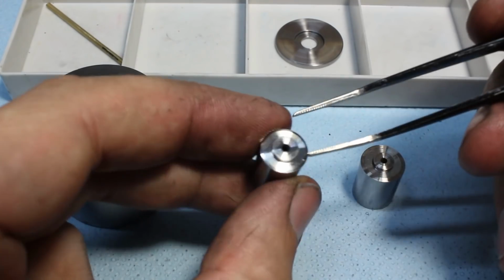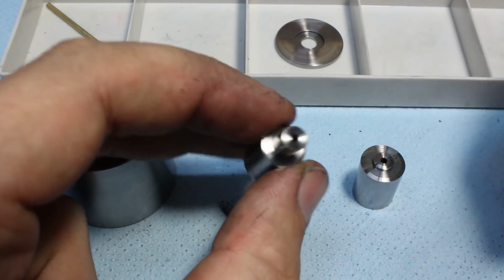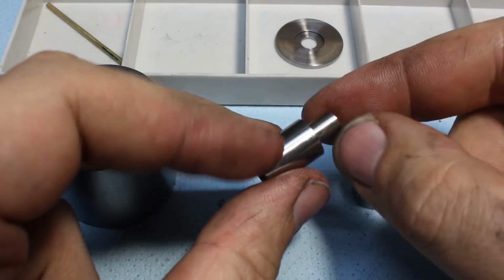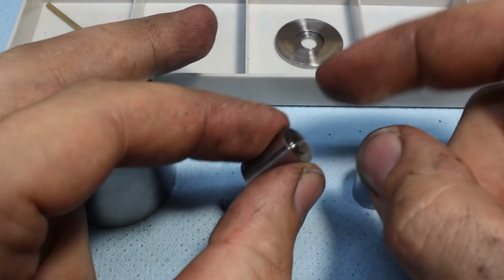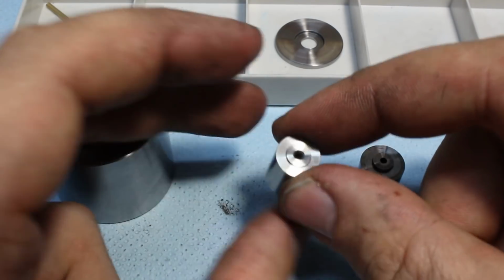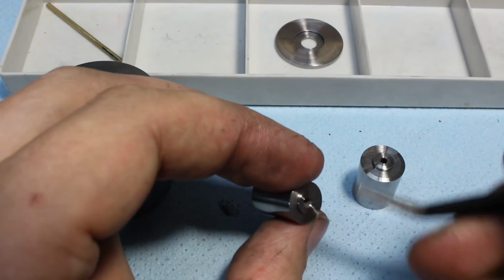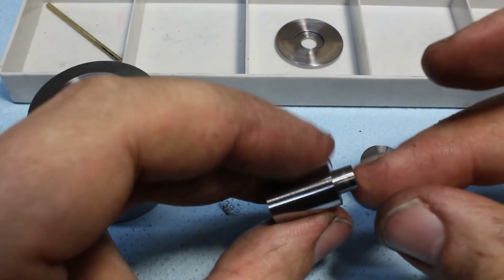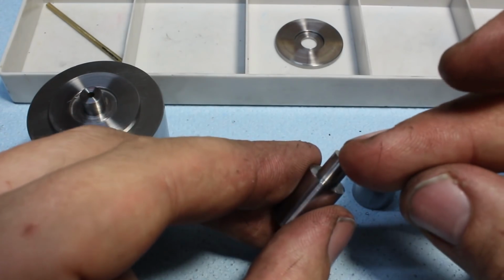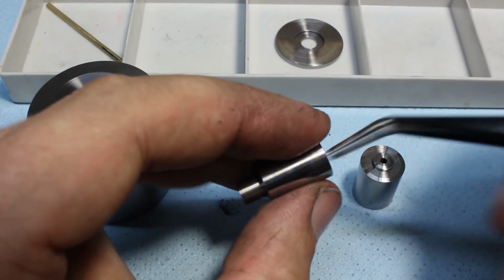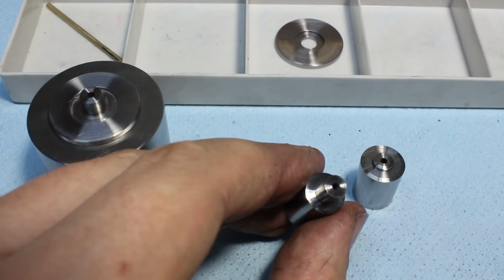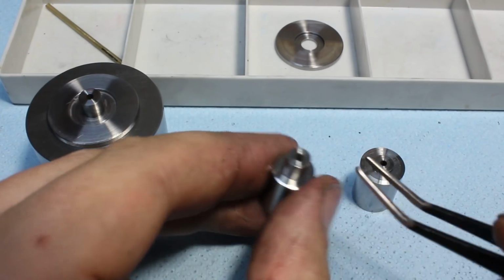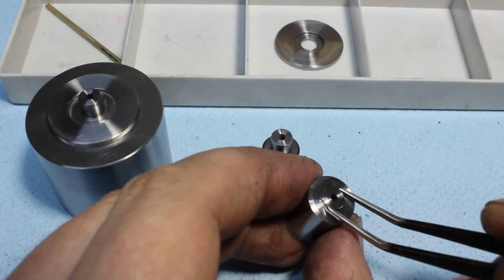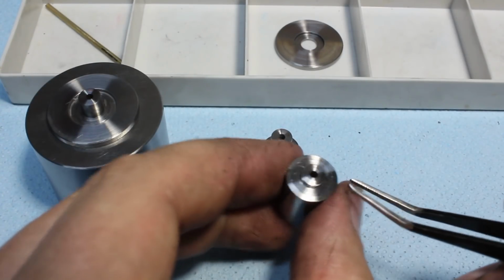Okay, I lapped all the IDs for these 6mm parts, and I got them to a very nice fit. Very nice sliding fit, but it doesn't fall out. So we're very close to an interference fit, which is perfect. In operation, these parts need to be sliding because they will be spring-loaded with some heavy Belleville washers and perform the metal forming this tool is going to do.